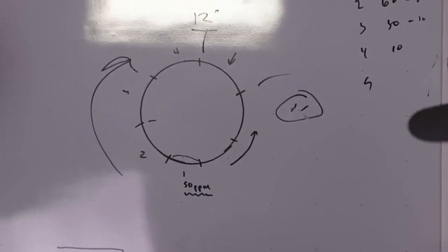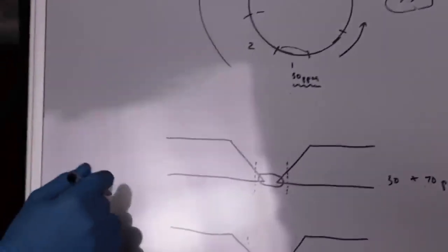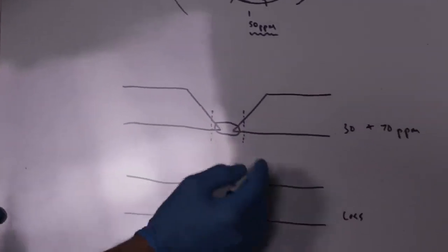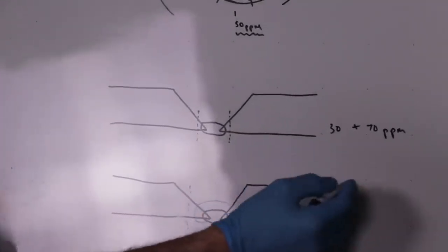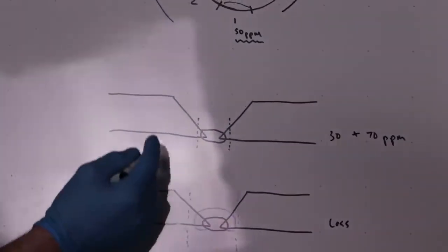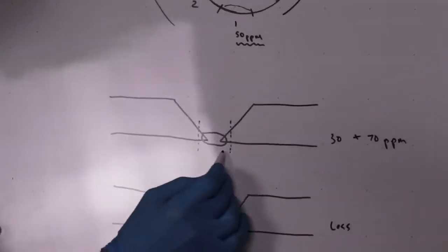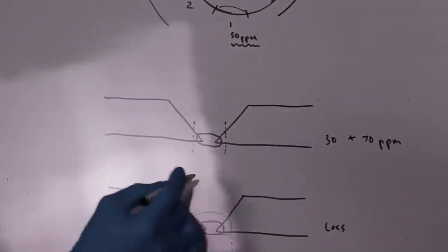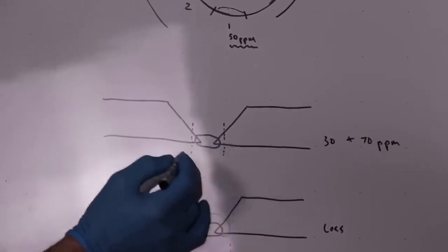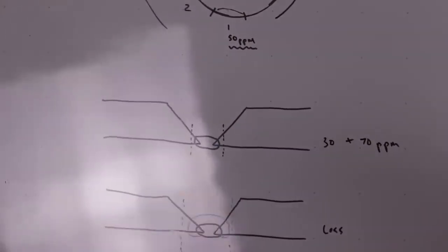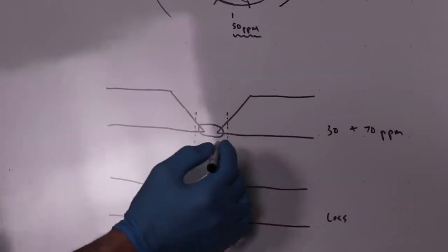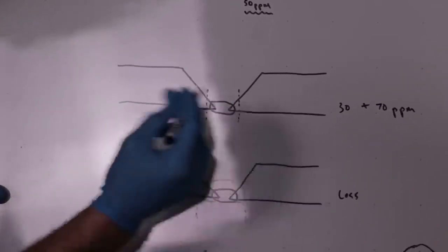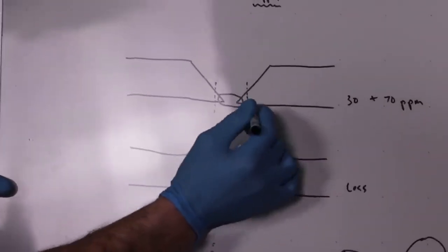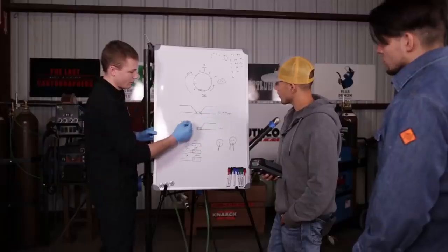Now, when we come down to any oxidization, any heat tint on the root pass, say, for example, your root was done at, say, 30, 70 parts per million, you might have light straw color, maybe gold, yellows, browns, etc. The root pass was usually about 1/16 of an inch on either side of the bevel. The heat affected zone is a certain width, and you're going to get a certain amount of oxidization depending on how many parts per million of oxygen are internally inside the pipe when you do the root pass.